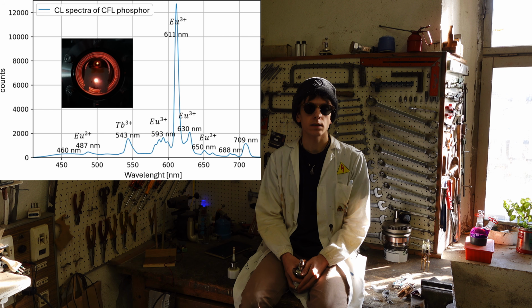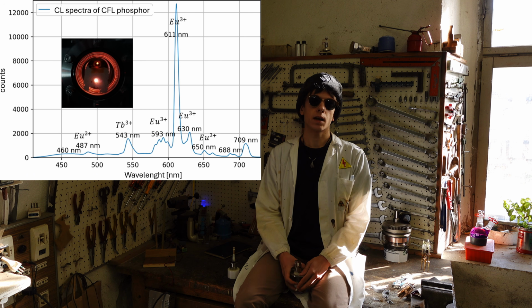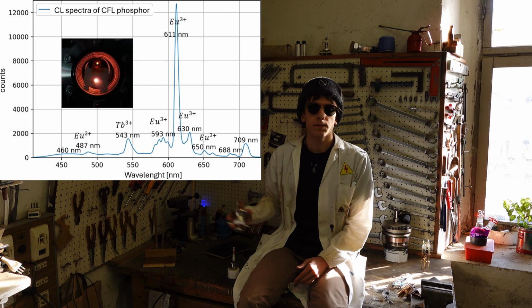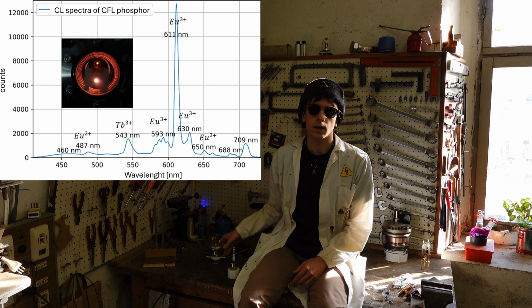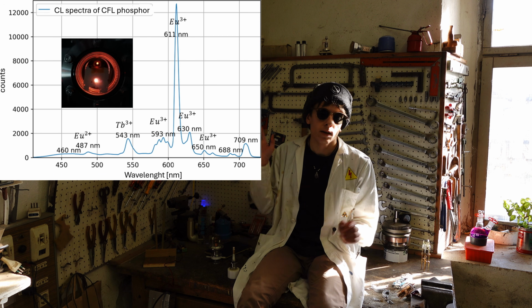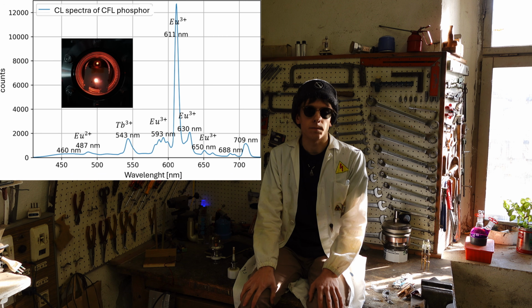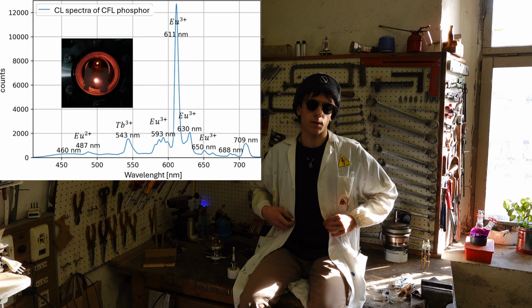We can do some example experiments like cathodoluminescence, so collecting the light emitted by a material being hit by electrons. This is, for example, the cathodoluminescence spectra of the phosphor screen I was using to measure the diameter of the beam. From this I was able to gather information about its chemical composition. In fact, each peak comes from an element present in the mixture. As you can see, it's a mixture of rare earth metals.